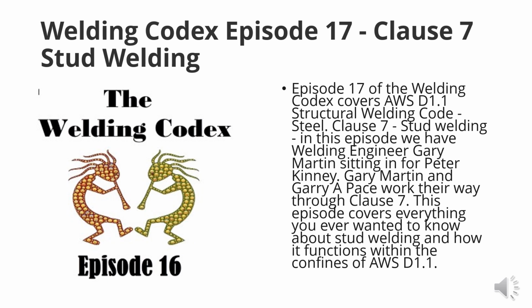So table 7.1, mechanical properties. This is the requirements for studs. Any thoughts here, Gary? Well, here's where we get introduced to the different types. So you've got type A, B, and C with 61 KSI, 65 KSI, and 80 KSI respectively on tensile. And then it gives the yield requirements, oddly enough, for the type C, that it goes to a 0.5% offset versus a 0.2% offset. Interesting, I didn't know that. And you don't have to have elongation for type C or reduction of area. Also interesting.